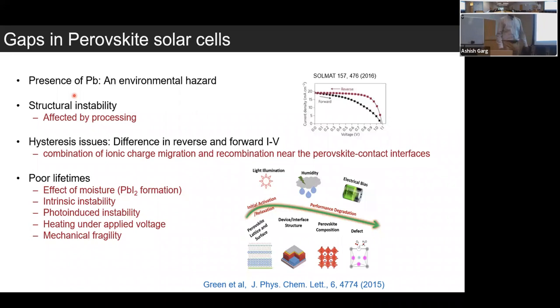The hysteresis issue is shown on the right. If you sweep your device in the positive direction or in the negative direction, some of the devices, if they have poor interfaces or ion migration issues, tend to have a difference in forward and reverse, which is not acceptable. For a good solar cell, the reverse and forward IV characteristics should be nearly identical.